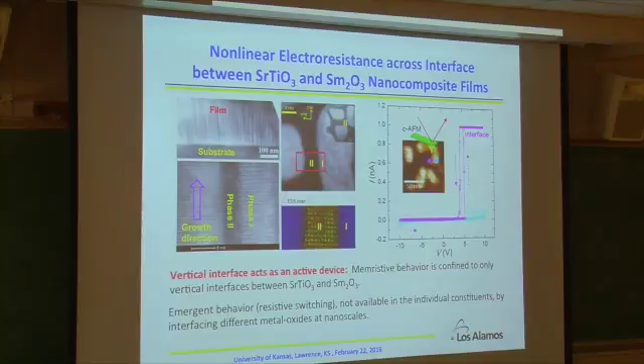Okay? Can you explain why this current versus voltage curve is not symmetric? See, when you sweep, you push up to like 5 volts, and then you see the conductivity, right? So your current increases from 0, let's say insulating, to say 1 milliamp. So it depends on the section. So you can calculate or estimate the conductivity. Why not when you push to negative 5 volts?